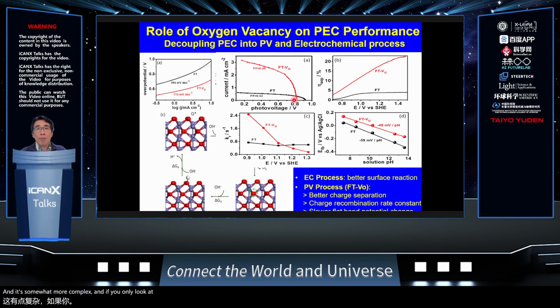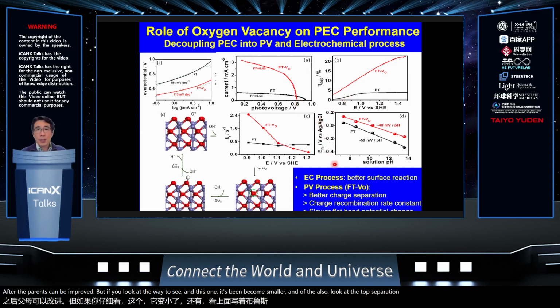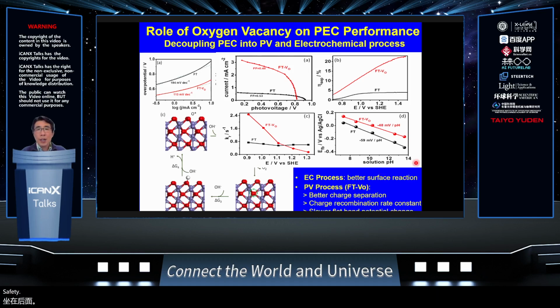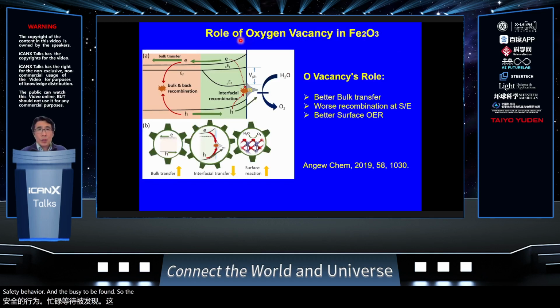If you only look at the photocurrent, the PV effect, after we introduce the oxygen vacancy, certainly the photocurrent can be improved. But if you look at the VOC, it has become smaller, and we also looked at the charge separation process, the charge recombination rate, and the flat band shifting behavior. Basically we found that the role of oxygen vacancy in this whole system can be divided into three key parts: in the bulk, that means in the film, on the interface, and on the surface. For the surface, this is the electrocatalysis process, and the oxygen vacancy is good for oxygen evolution. In the bulk, it can also help the charge transfer behavior.